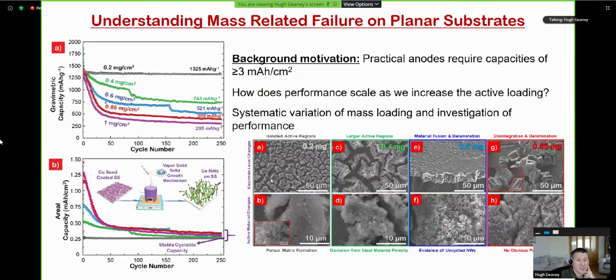So the first point was to see, could we understand this? On the lowest loading, the 0.2 milligram loading, we found these nice isolated active regions of the material. And then as we zoomed in, we had the lovely porous network that Ty had previously seen. Again, that was all consistent with what we had seen before. But as we started to increase the loading, we started to come up with new materials-based issues. At 0.4, we had larger active regions. You can see these are at the same magnifications, but the active regions are larger.